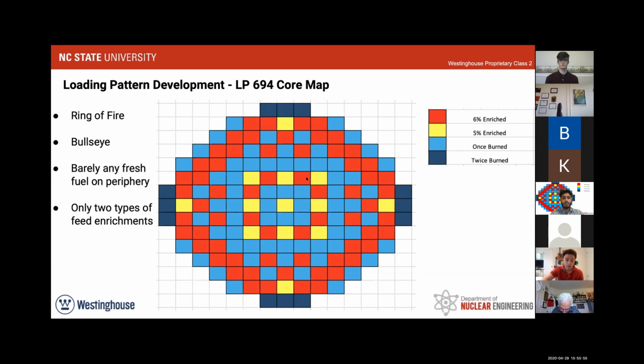So this was really one of the best ways that we could manage our fresh fuels and still meet peaking. And you can also note that to increase our neutron economy, we had barely any fresh fuel in the periphery, where only one side of the four sides of the fuel assembly in each quadrant was exposed directly to the core periphery. That went a long way in limiting our neutron leakage. We were also able to get by with only using two types of feed enrichments, 6% and 5%. That was a secondary goal, to help with manufacturability, so manufacturers can focus on just producing these two enrichments instead of more than two.